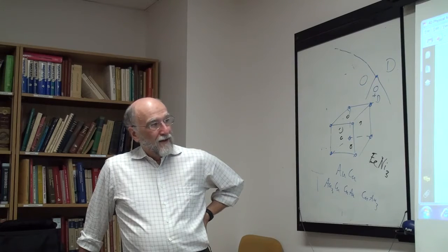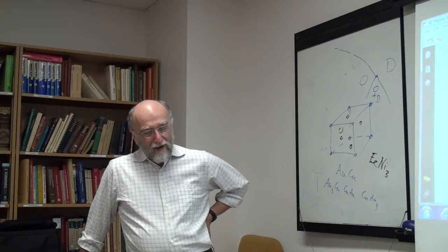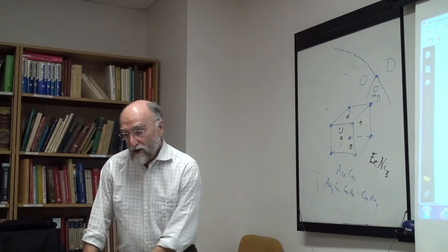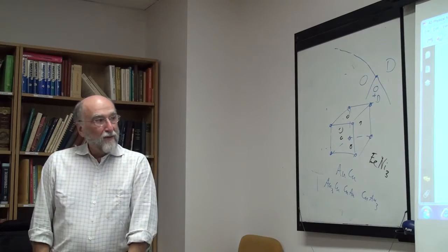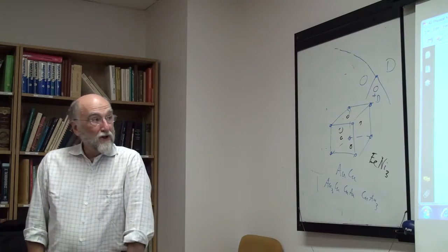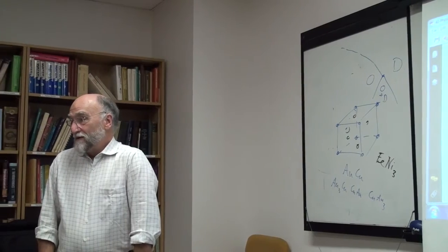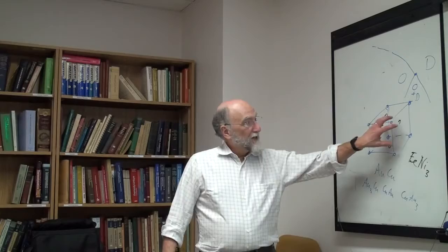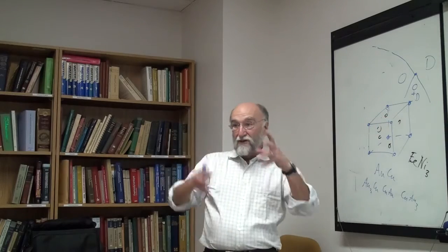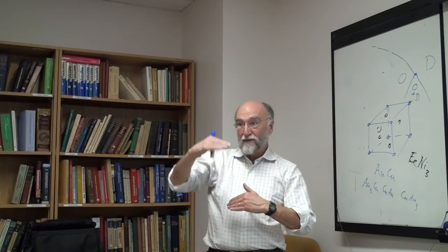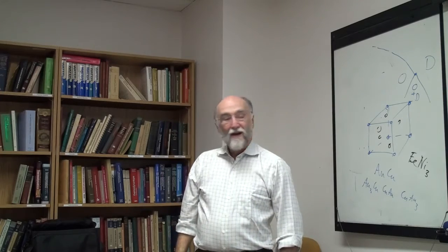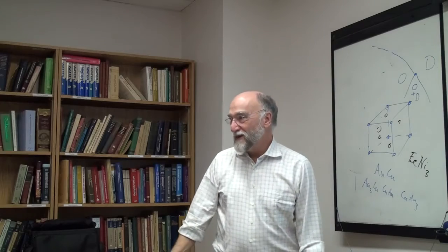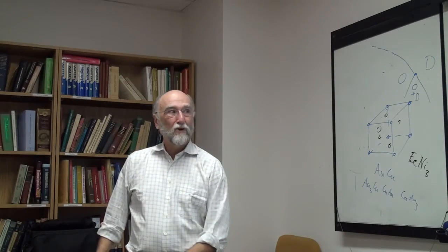Because you know that the configurational entropy expression in the pair model, in the modified quasi-chemical model, is complicated enough and is only good when z equals 2. Now, when you go to a cluster variation method, and they're putting tetrahedra and octahedra and moving these things all around, they end up with an entire page of terms in the entropy expression. And it's really an approximation, which is only good when z is 2, and what does that mean? This is never mentioned. I don't know if I believe this stuff.